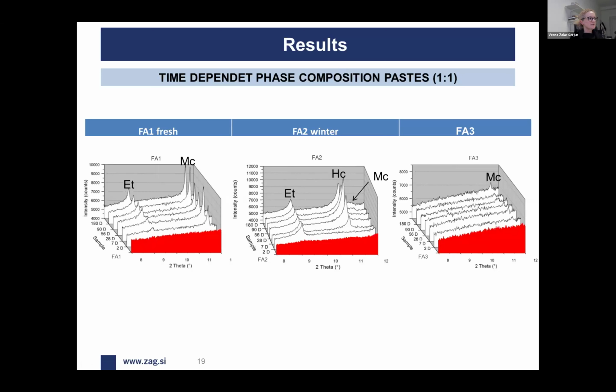Here you can clearly see that some hydration products were formed with the increase of time interval. In the first case, ettringite and monocarboaluminate. In Fa2 winter, which showed the largest heat release, ettringite is also formed, hydrocalumite, and also, to a smaller degree, monocarboaluminate. Those are all so-called AFm phases, which represent the typical hydration products of cement hydration. In the Fa3 case, something little is happening, but in general, nothing is happening, which confirms the isothermal calorimetry results we looked at one slide before. Also, the relative intensity of hydration products formed is the highest in Fa2 winter, which again supports the results from the heat release.